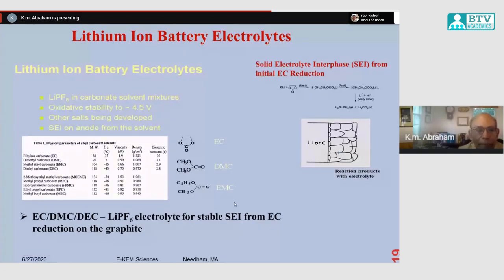very active even today. And the lithium salt, you need a lithium salt along with the solvent to form the electrolyte. And the commercial batteries use lithium hexafluorophosphate. It's a complex anion salt of lithium cation. So you form a Li+ PF6-.